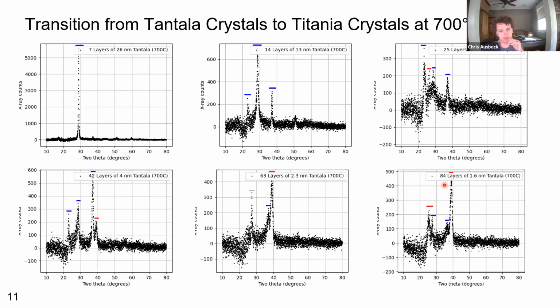And then at 84 layers of 1.6 nanometers, we see that the titania peaks are now much greater than the tantala peaks. We see both the 26-degree peak as well as the 39-degree peak. And then we also see the 29-degree peak of the tantala as well as the 36-degree peak of the tantala as well.